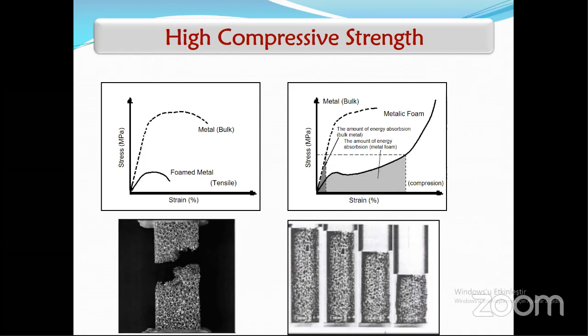When we look at the mechanical properties of the samples, this is the tensile behavior of foam material and bulk material. The tensile properties of foam material are not good because of the lots of porosity in the sample, which act as a notch effect. That's why it reduces the tensile properties of the samples. But the compressive strength of the sample is quite good. That graph shows the compressive strength of the bulk material and the metallic foam. The dark area here is the amount of energy absorption of the bulk material. That's the small area. This open gray, that big area, is the amount of energy absorption of the metallic foam. So we can say that the compressive strength of these materials is quite good.